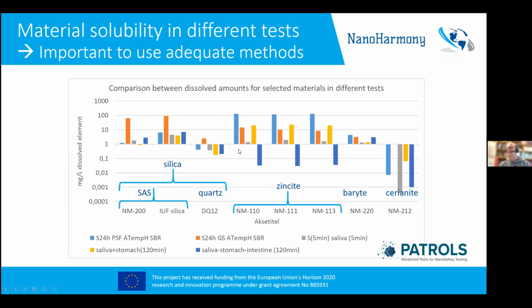Then we move into the zinc oxides, and we see a somewhat similar pattern across all 3 types of nanomaterials. Here we have uncoated nano zinc and coated nano zinc, and a large nano/small micro-size zinc oxide here. We see the same pattern: very high dissolution in the phagolysosomal fluid, to some extent in the lung lining fluid, and then variable solubility in the gastrointestinal fluids. And then we move to the barium sulfates and cerium oxides, which have relatively low solubilities in these media, at least for the cerium oxide.